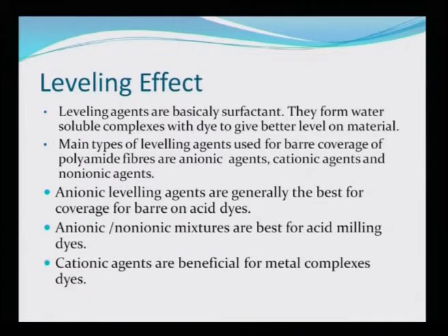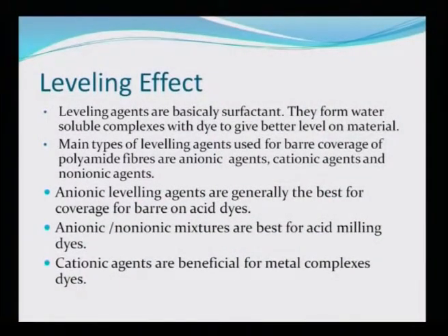So, if we use acid dyes along with anionic leveling agents, it is the best combination, because that starts promoting the protonating of the amino group of nylon 6,6. Similarly, cationic agents are good for metal complexes, because they start initiating the reaction by protonation.